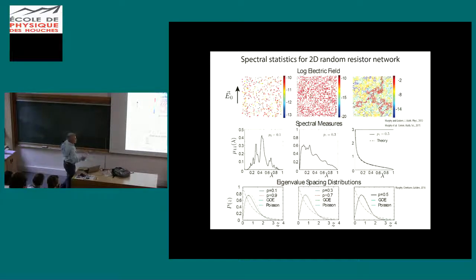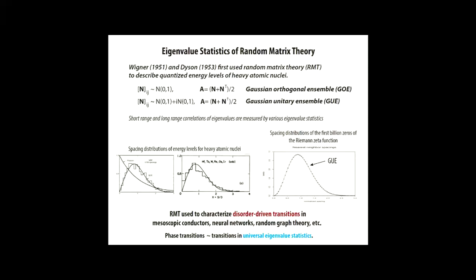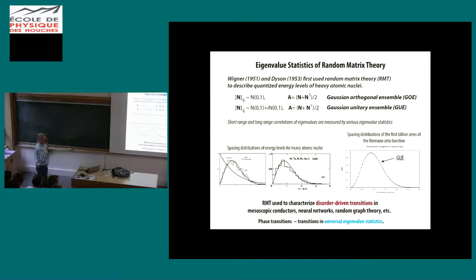But then as you develop long range order in the system and you start to approach this percolation threshold, the distribution of the eigenvalue spacings approaches these so-called very famous Wigner-Dyson universal distributions, in this particular case known as the Gaussian orthogonal ensemble distribution. And this sort of led us unexpectedly into the world of random matrix theory, developed by Wigner and Dyson, first used to study the very high number of quantized energy levels in heavy atomic nuclei. And you have Gaussian orthogonal ensemble, Gaussian unitary ensemble based on the matrices.